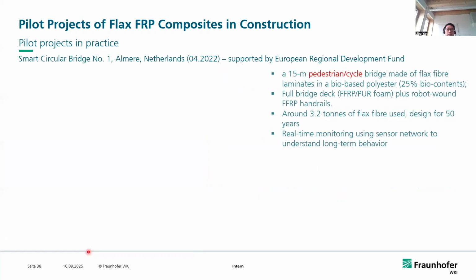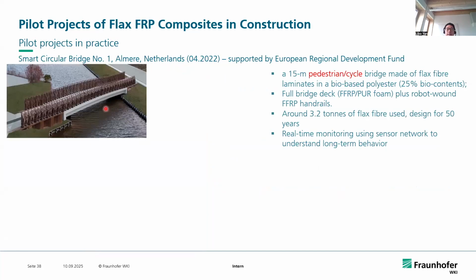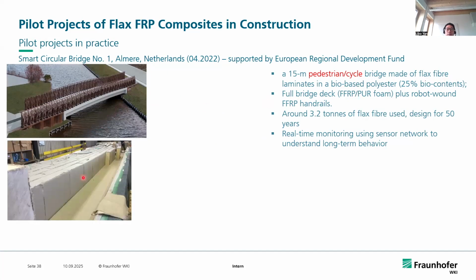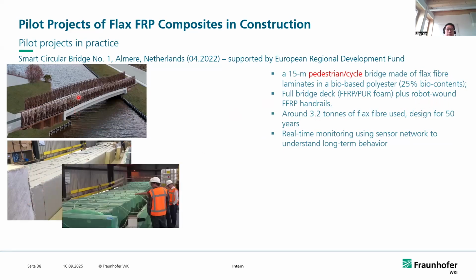In 2022, still in the Netherlands, the Smart Circular Bridge #1 was opened. This is a 15-meter pedestrian and bicycle bridge made of flax fabric composites in a bio-based polyester. The full composite deck is made of the flax FRP and PUR foam, and the robinia wood and flax FRP are used as the handrail of this project. In total, about 3.2 tons of flax fabrics were used, designed for 50 years, with real-time monitoring using sensor networks to understand the long-term performance.